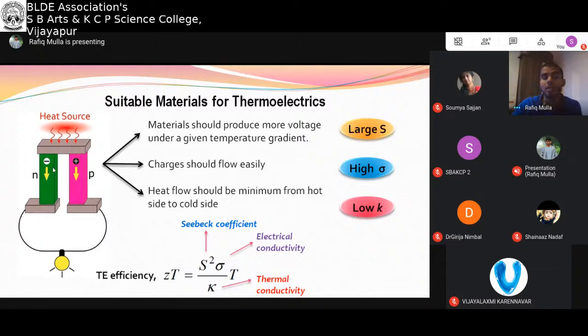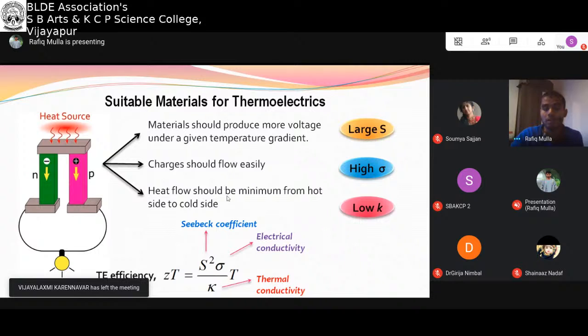If charges suffer, or if we take any insulator, the movement of charges is very difficult, even after the application of temperature gradient. So we need materials or conductors in which charges can flow easily. And another requirement is heat flow should be minimum from hot side to cold side. That means when we apply the thermal source on one side, the other side should always be at lower temperature as compared to this side. So if this side temperature becomes this side temperature, then there is no temperature gradient across the device. When there is no temperature gradient across the device, then there is no voltage production from the device.